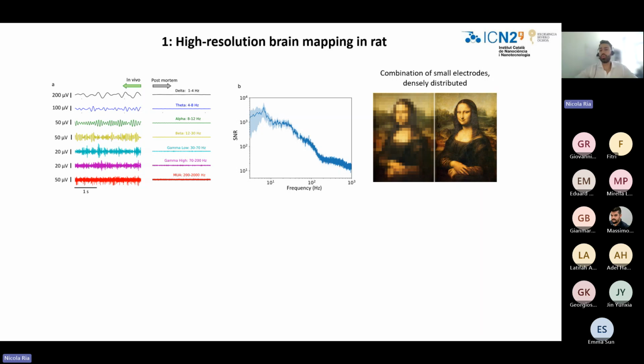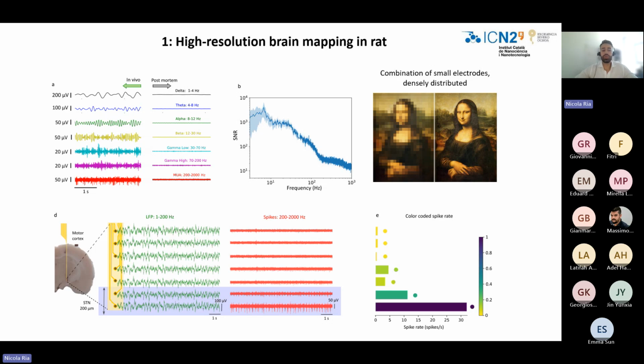The combination of very small electrodes, densely distributed, and also capable of recording with high signal-to-noise ratio, allows the localization of the subthalamic nucleus by looking at the recording activity through the different electrodes of the array. The subthalamic nucleus is very small in the rat, only 200 micrometers, and it is also placed quite deep in the brain, around 7.7 millimeters. So it is a very difficult target to reach.